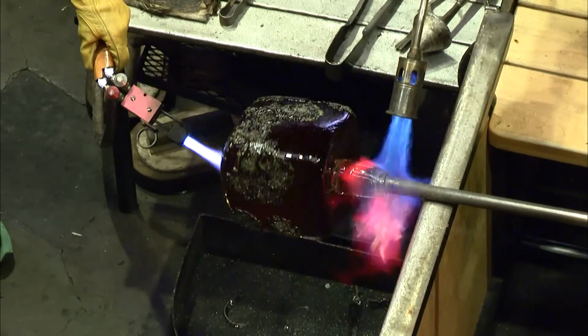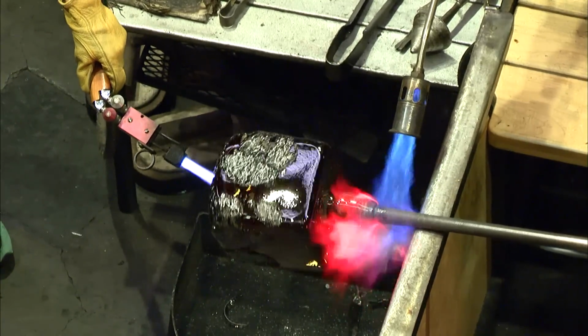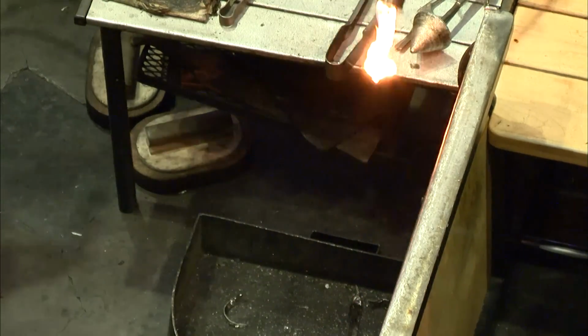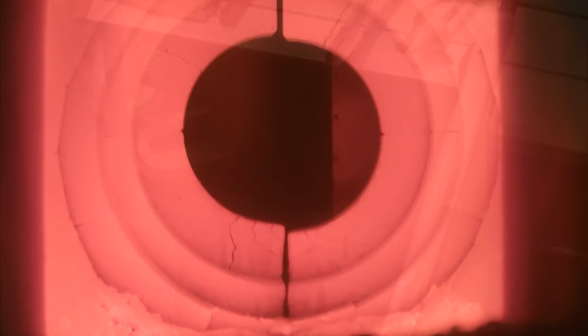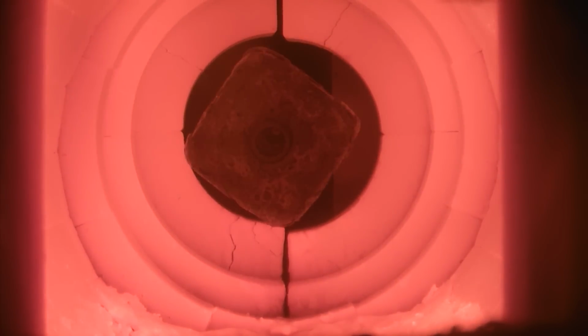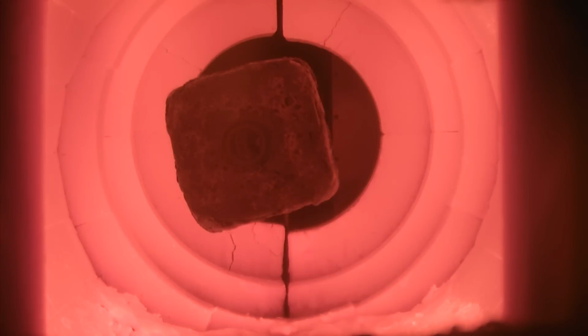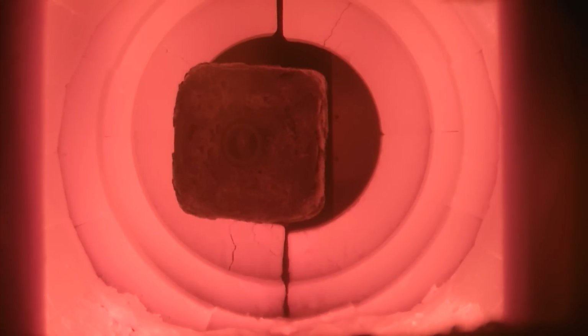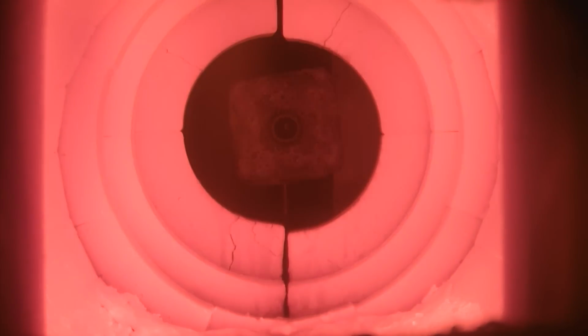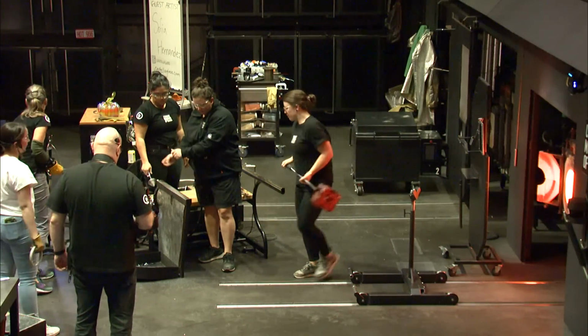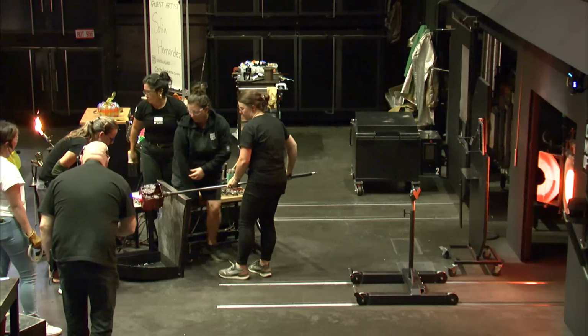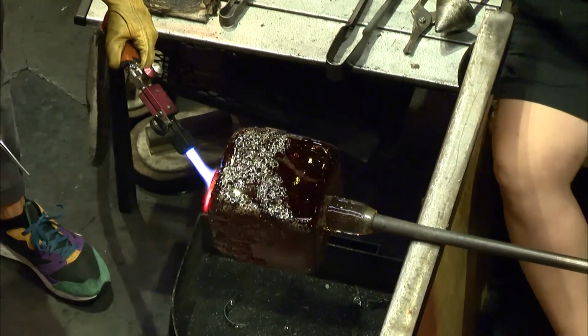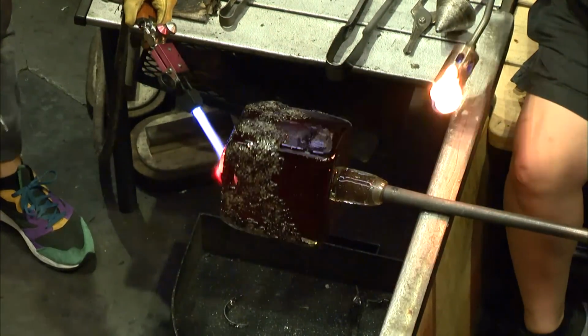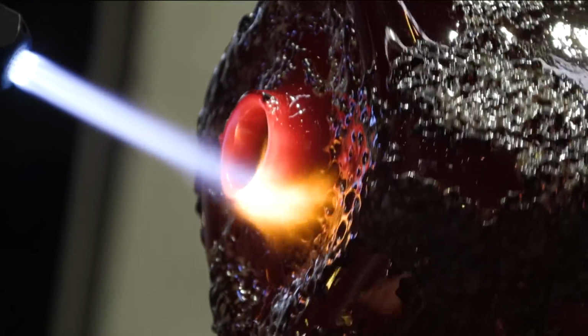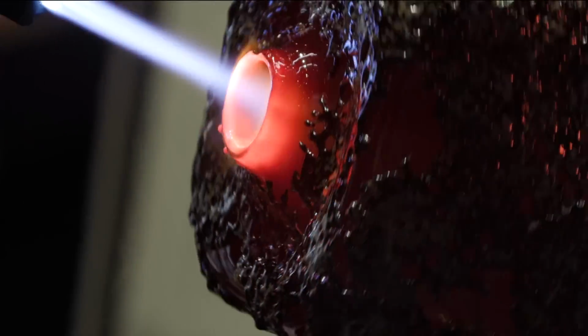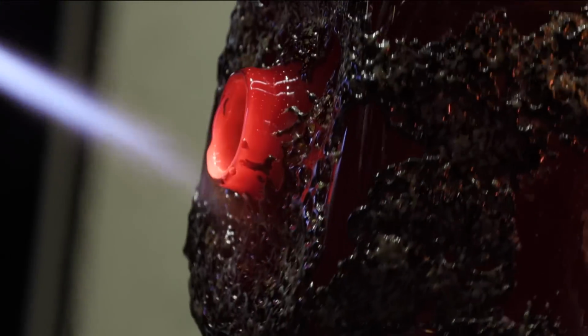But they would work it a little bit differently too, because when we're finished with our process, we take the piece and put it in a separate oven and cool it electrically, using electric heating elements, because there's a lot more control. In ancient times, they would put the finished glass in a chamber above the melting furnace and then close everything up when the crucibles were drained, and everything would cool down as a thermal mass together. So that was the earliest way they started cooling the glass slowly, putting it in their kiln above the firing chamber and letting everything cool down together. Just stop firing, plug it up. And that's the most basic way of cooling the glass properly, annealing the glass. And then a lot of different techniques developed from that.